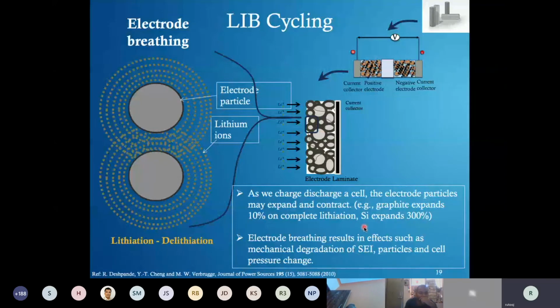For example, a graphite electrode will see about 10% expansion on complete lithiation. Whereas if you want to use silicon as your electrode, for your information, silicon has much higher energy density than graphite. But the problem with silicon is it has 300% expansion. So your cell may be much bigger when you charge the cell than when you discharge the cell. So there is this continuous expansion and contraction happening within the electrodes, and this is called electrode breathing. Now there are several effects that are happening as a result of this electrode breathing. We'll go through some of them here.